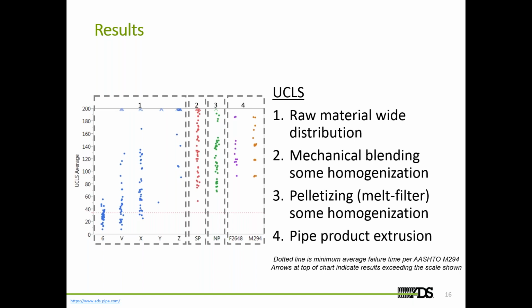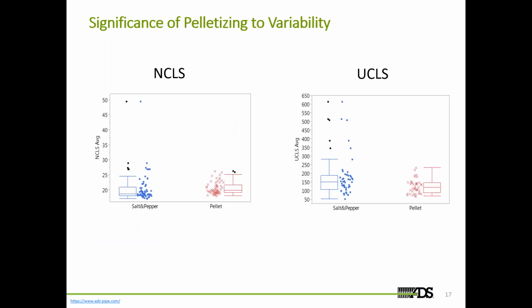So you can see there's a pretty large bump in performance in the UCLS just by salt and pepper blending all of those raw material streams, and we get another fairly sizable bump in performance when we pelletize that material. So that's the NP column, and then as we make it into pipe, into both F2648 product and M294 pipe product, the material performance in the UCLS test increases even more. So again, when we're looking at the significance of pelletizing to variability, when we're taking our raw material streams, it helps if we salt and pepper blend, but it actually helps even more if we pelletize that material. So that's why, when Dr. Plumier spoke about pelletized material, you could make pipe out of flake if you really wanted to, but in reality, you really shouldn't make that M294 product out of flake. It's better to make it out of pelletized material because you get a more consistent result.